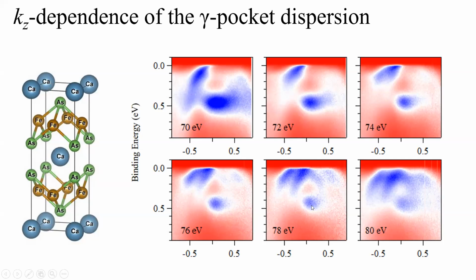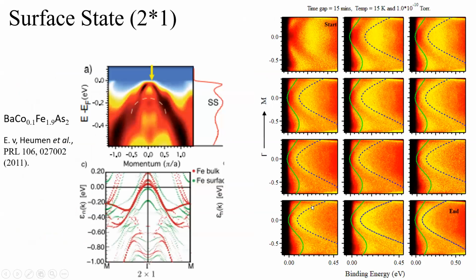So the cobalt doping is shifting the band positions, which is expected because of the charge carrier doping. It's creating a huge amount of correlation that basically leads to renormalization of the bands, and it's also changing the dispersion or the renormalization factor at different kz values.